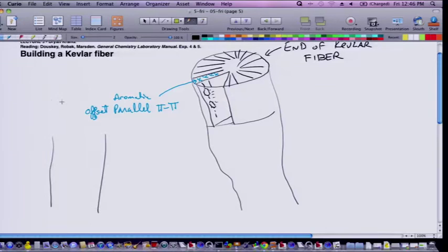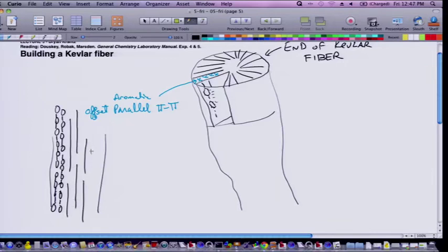It's really quite infinite. And if you were to look at these fibers, and these are aromatic rings, sometimes let's say a fiber would terminate in the middle of a sheet, then another fiber would just pick up right underneath it. Okay? And then say a neighboring fiber would actually be contiguous next to it. So it would effectively glue any defects that you would find together in these polymer sheets. And so you'd have offset and staggered polymer chains throughout, gluing together these sheets.